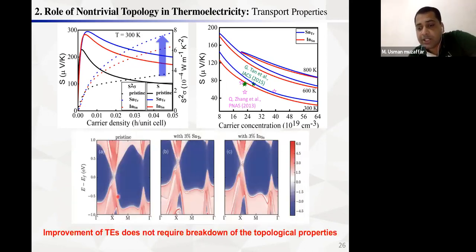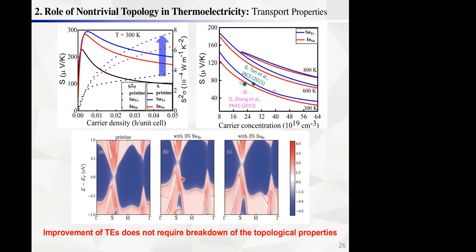So these are the topological properties. As I mentioned earlier, SnTe is intrinsically already topologically non-trivial, and after the anti-site doping, 3% doping, the system still remains in the non-trivial regime. And in the indium doped SnTe system, the system is also in the non-trivial regime.